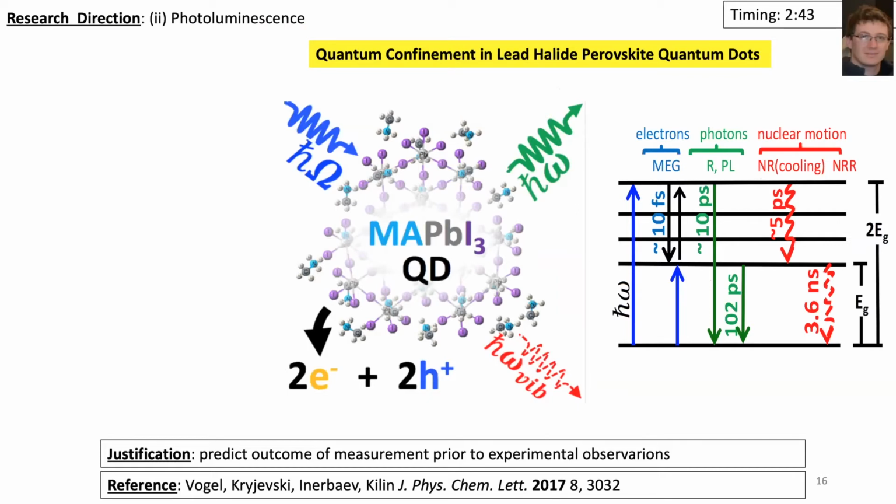So we just tried to look on the couple of elementary processes and compare their rates, and it looks like there is a competition with several photoexcited pathways of relaxation, like radiative recombination, non-radiative recombination, the relaxation from higher excited to lower excited through energy dissipation, and simultaneously there is a change of the number of excitations from 1 to 2, just made by this Fermi's golden rule approach.